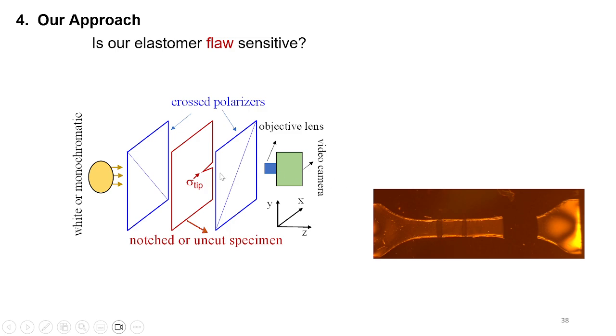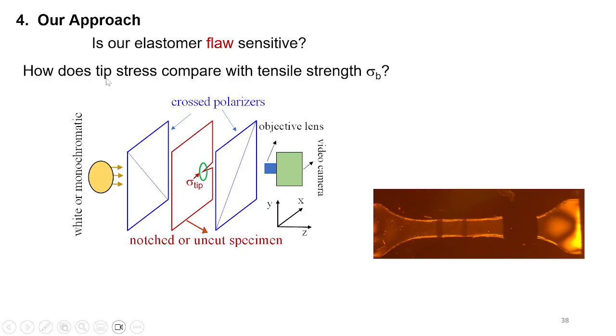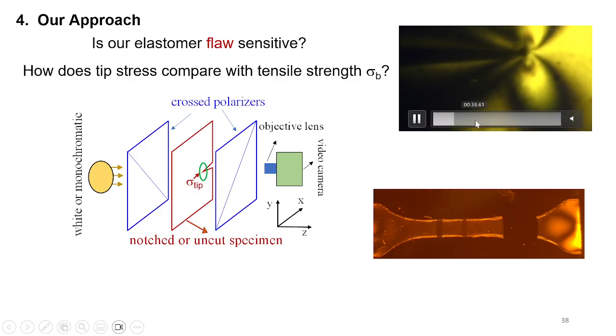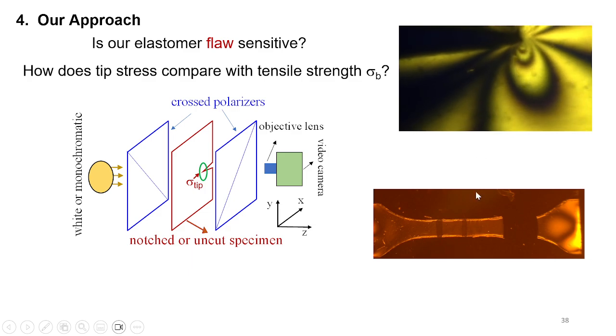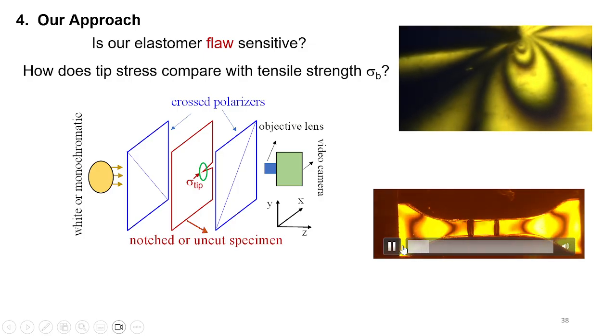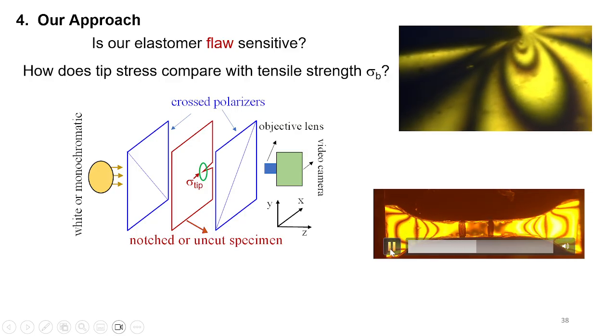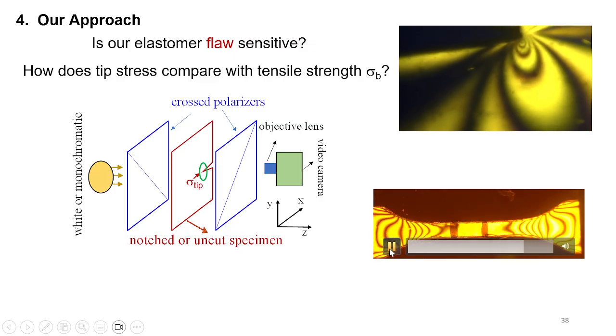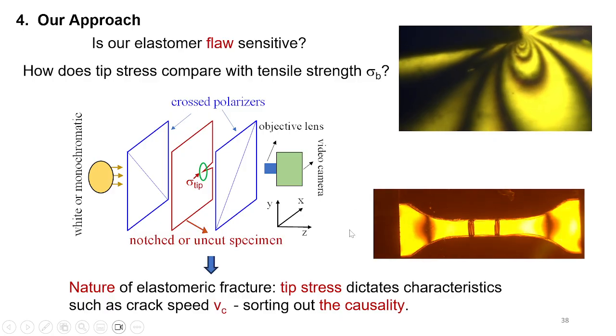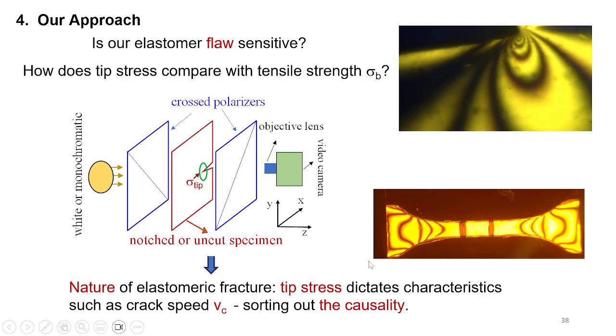So we decided to look at the tip directly and to look at the stress at the tip and to even compare that stress at the tip with the tensile strength. Through that, we can learn about whether a flaw is really the problem. Okay, so here is one where we intentionally make a flaw and stretch it. It turns out that you can patiently analyze this movie and find out through birefringence what is the state of stress at the tip. And start to ask the question of why, at the higher load, the crack speed is higher.